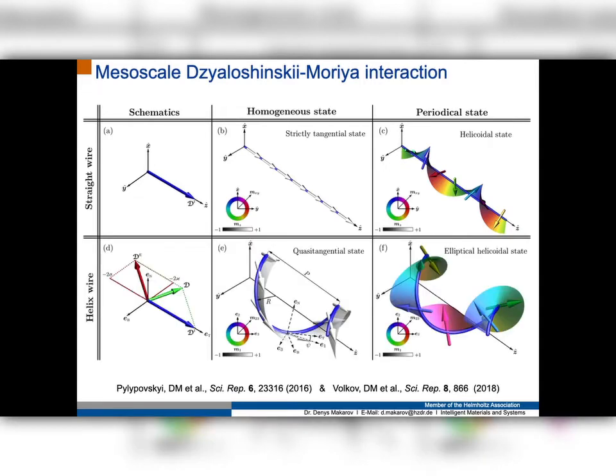In case of a curvilinear helical helimagnetic wire, you will have the possibility to modify the homogeneous state due to the curvature-induced anisotropy, which will result in a tilt of the magnetic easy axis away from the tangential direction, and at the same time the helimagnetic phase transition will now be determined by the vector of the so-called mesoscale Dzyaloshinskii-Moriya interaction, which is a vectorial sum of the intrinsic Dzyaloshinskii-Moriya interaction and the extrinsic one, which comes from the geometry, from torsion and curvature of this space curve. If you have a possibility to change the helimagnetic phase transition by geometry, you can come up very nicely to the possibility to create a memory.